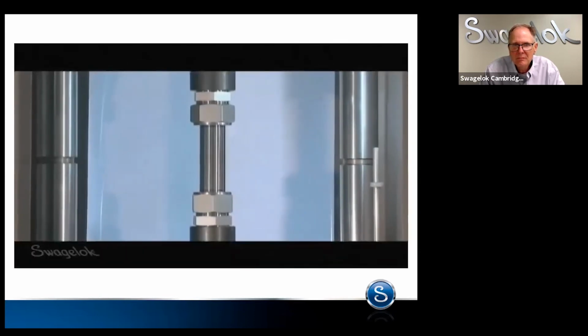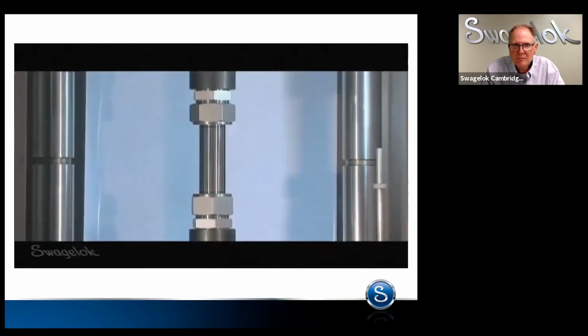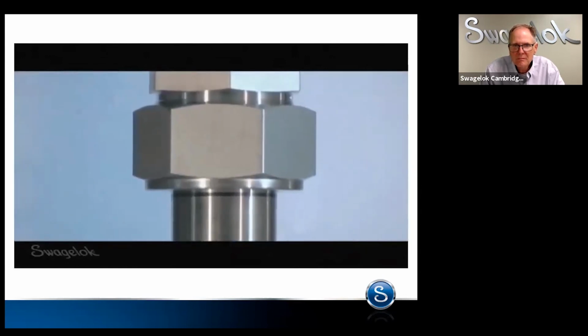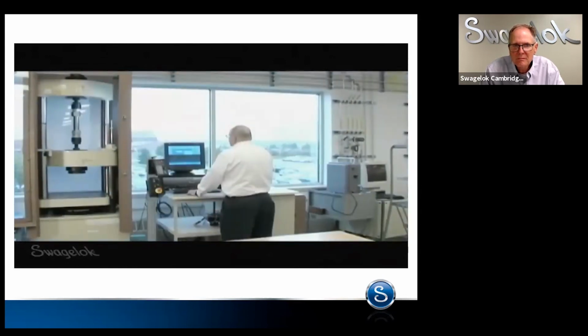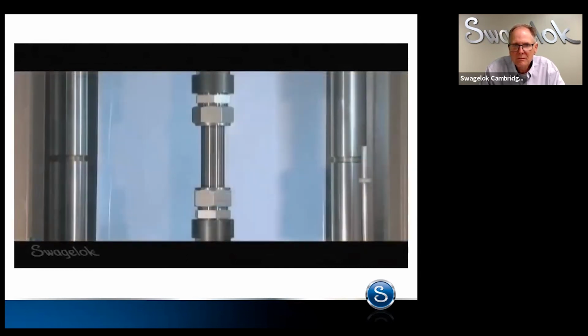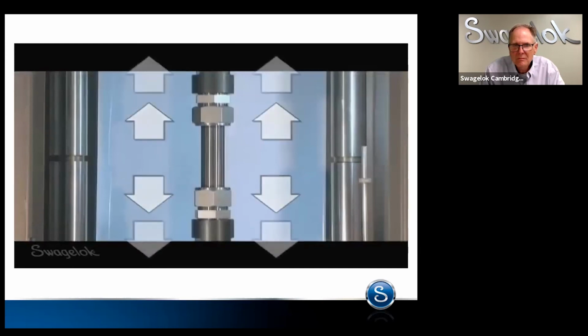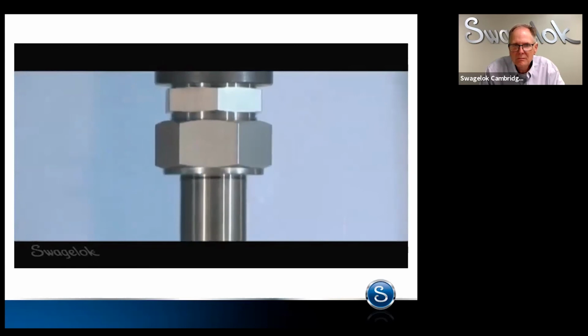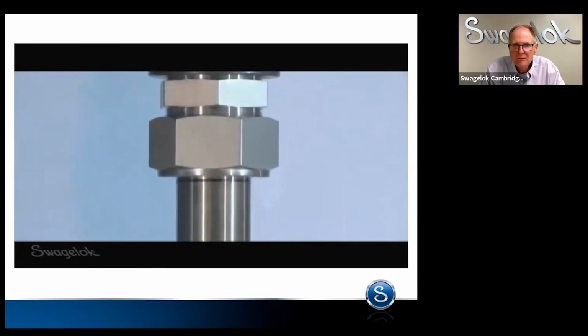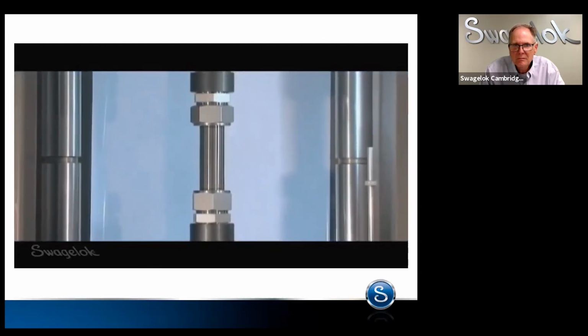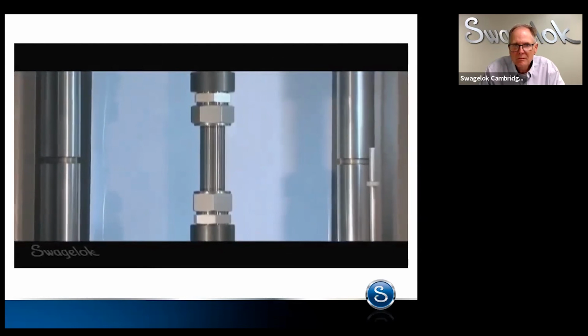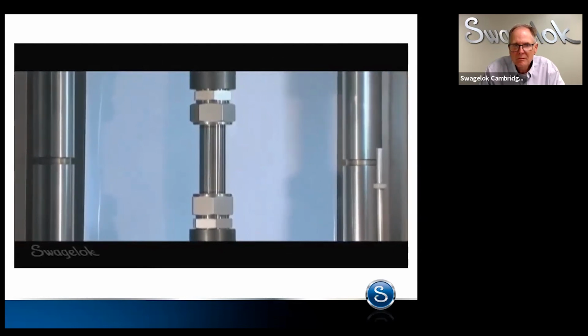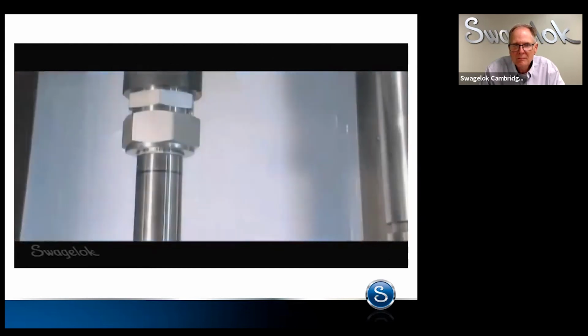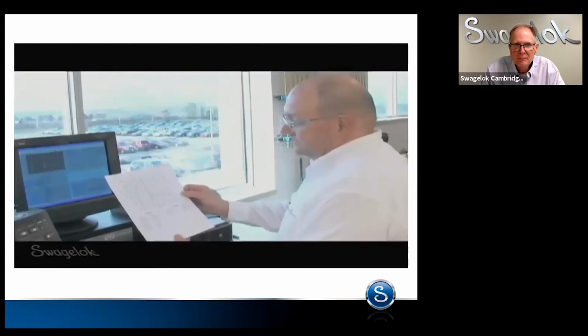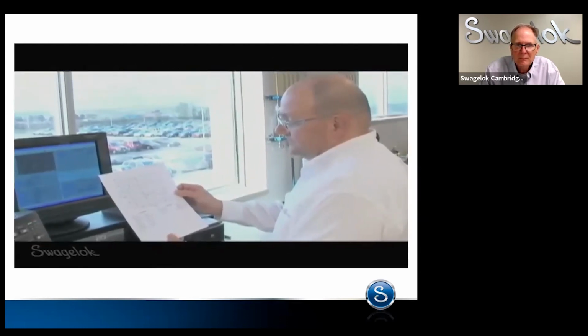A tensile pull test is used to demonstrate the effects of unsupported weight on tubing and fitting connections. This test is being conducted on a 2-inch stainless steel Swagelok tube fitting at our Swagelok product test lab. The weight load is increased by pulling each end of the tubing at a rate of 1/4 inch per minute. The test is designed to compare the maximum load that the tensile pull reaches before the tubing is forcibly pulled from the fitting. This assembly reached a load of over 45,500 pounds, which is the equivalent of 14,465 psig, well above the American Society of Mechanical Engineers calculated burst pressure of 13,500 psig for 0.188-inch wall thickness